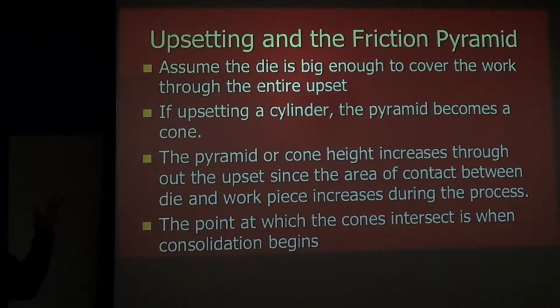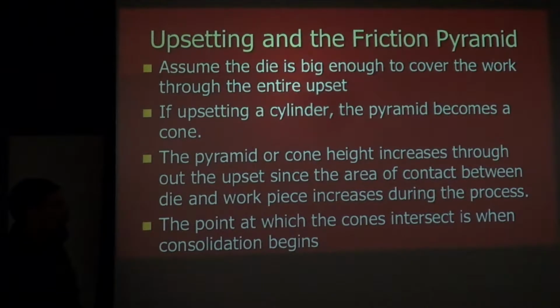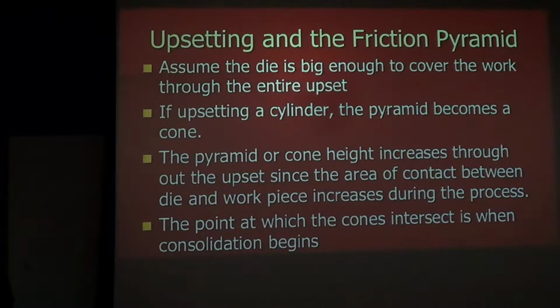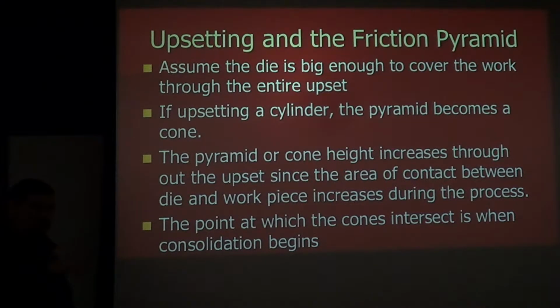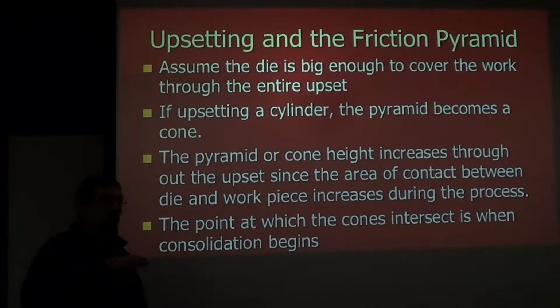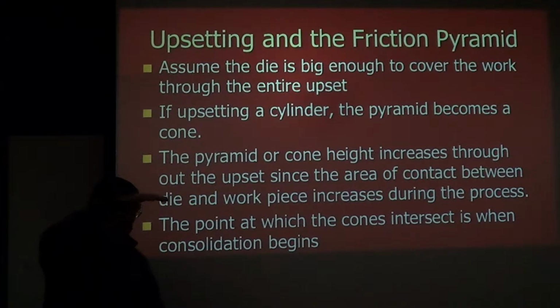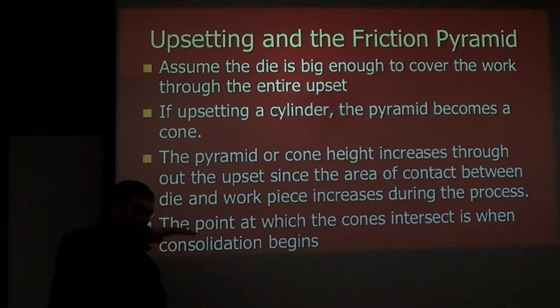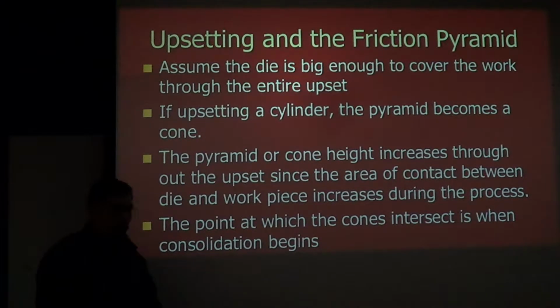And we're also going to say that if we have a cylinder, instead of having a pyramid, we have a cone for our friction. So in this case, a friction cone. So the height of our pyramid, or our cone, will change. In this case, it's going to increase because the amount of metal in contact with the die is increasing, the diameter is increasing, so therefore the height of the pyramid is also increasing as I move through the process. So this is a process that's typically done in one push. I'll take my starting piece, we'll put it between the dies, and we'll just push. And we'll just keep going until we reach the new height that we want.